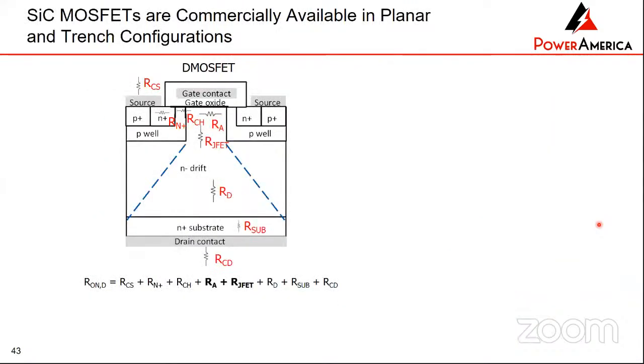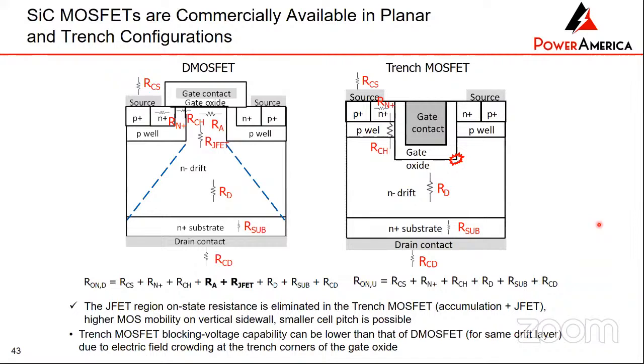So just to give you an idea between the planar and the trench MOSFET, in the planar MOSFET that's shown here, you have the channel resistance right here, and then you got this JFET resistance here. If you go to the trench MOSFET, then you eliminate this JFET resistance. The conduction is happening in this vertical direction, but the problem is because it's a trench, the corners of this trench are susceptible to high voltage issues, okay?